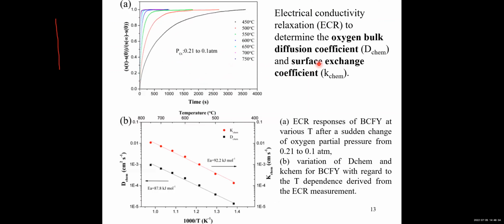So we conducted ECR measurements, and we observed improved oxygen bulk diffusion coefficient and surface exchange coefficient.